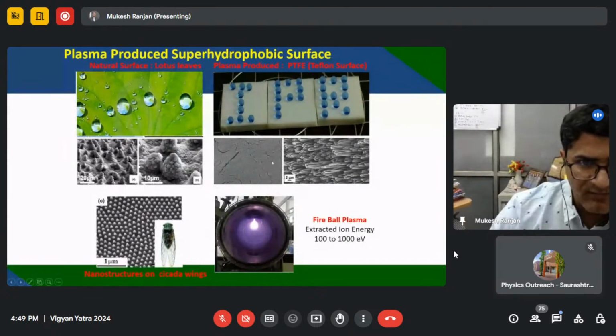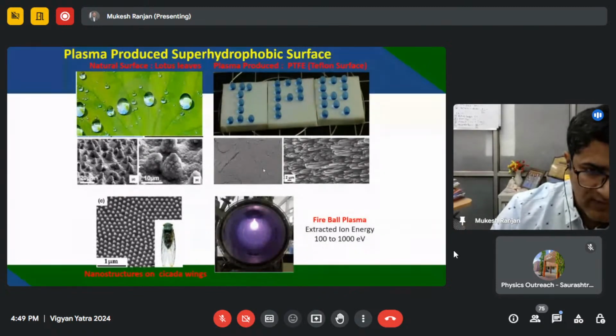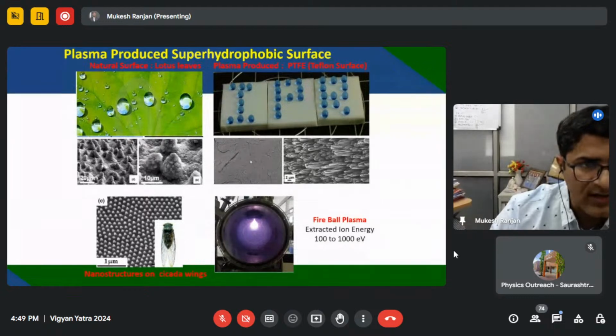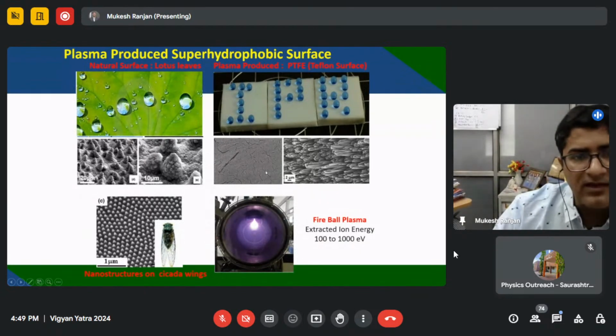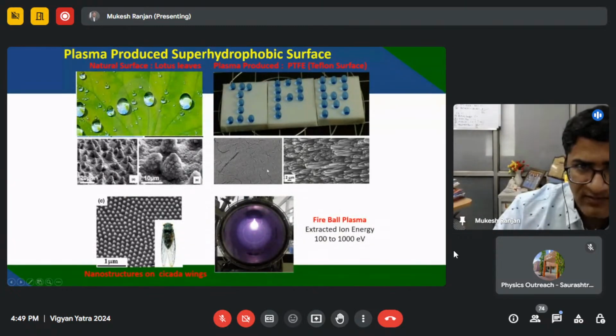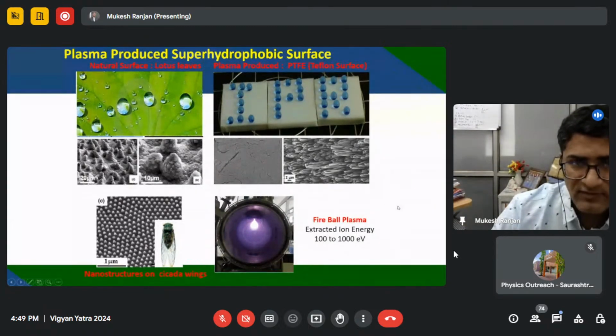So initially it has some roughness, and this is an example of Teflon. Teflon is by nature hydrophobic, and the water contact angle is around 100 degrees. But if you treat it with plasma, it can make some nanostructures like those on the lotus leaf. And this nanostructure can make this Teflon super hydrophobic, and the droplet actually starts rolling on the surface. So that's the reason why, by tuning your plasma parameters, you can make the surface either hydrophobic or hydrophilic.